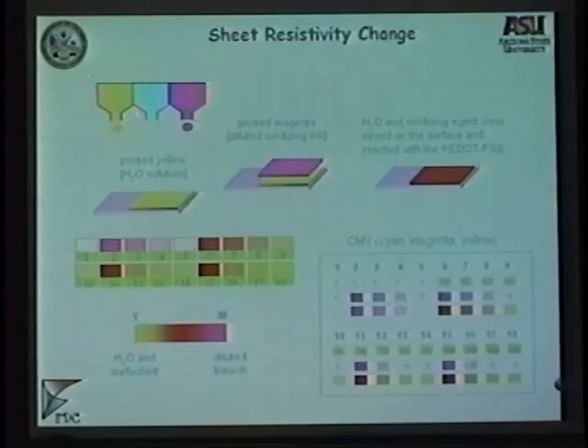But we put DI water in this chamber of the inkjet, and then we put a bleach like sodium hypochlorite in this chamber, and then we start mixing these on the substrate. So we're doing chemistry using inkjet right on the surface of the substrate. Of course, you can't deposit the bleach first with the inkjet. You have to deposit the water, otherwise the bleach will eat out the whole PEDOT on the substrate and render it extremely insulating. So these are about 5 to 10 picoliter drops.